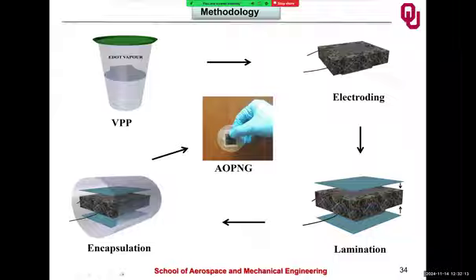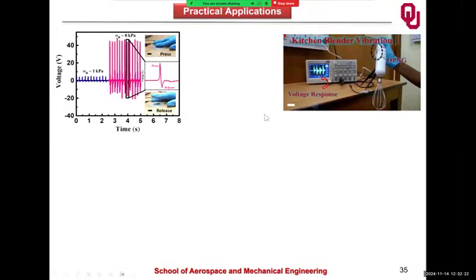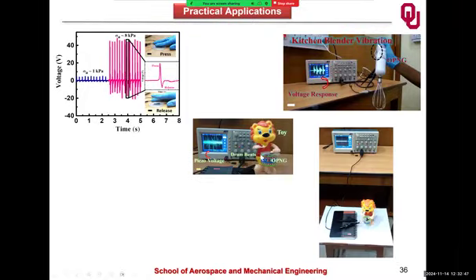Finally, after getting that fiber and making the electrode, we encapsulated it with a soft polymer matrix, and this is the device we fabricated. And here is the practical application: when you apply pressure and release by simple finger touch, it can generate voltage. Not only that, we also used that nanogenerator in household applications like a kitchen blender. We attached our sensor on the kitchen blender, and for the vibration on and off, there is some voltage response. And we also used one example, very funny, where we placed the nanogenerator on a toy, and with the drum beats of the toy, it can generate voltage.